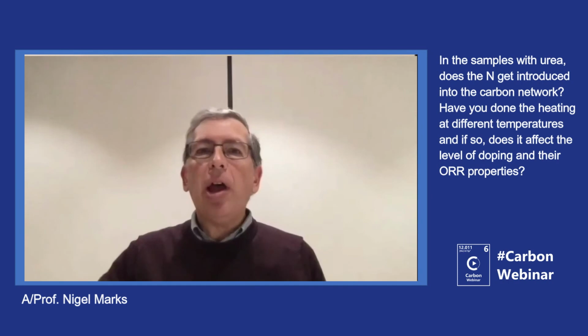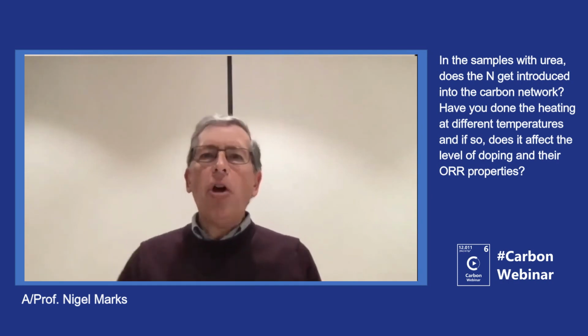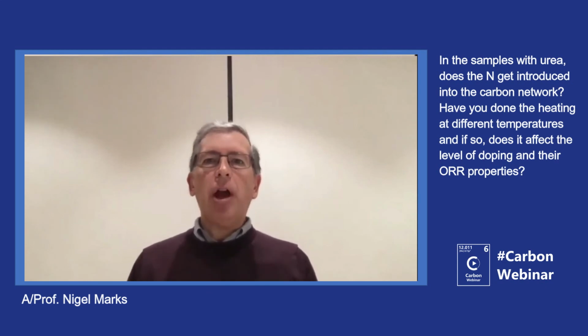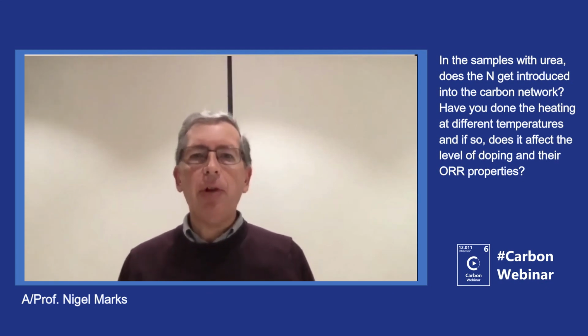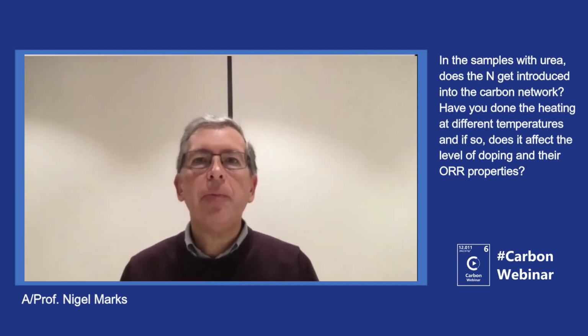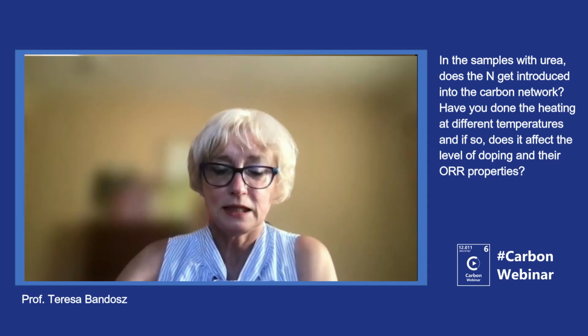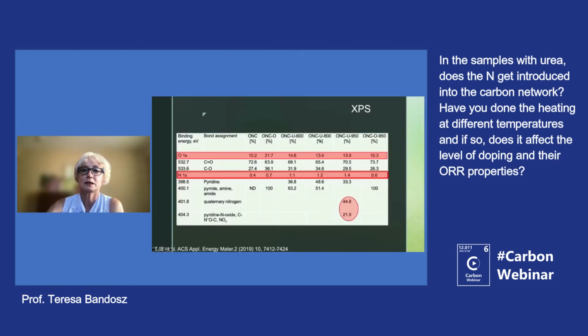Okay, so in the samples with urea, nitrogen gets introduced into the carbon network, and have you done the heating at different temperatures? And if so, does that affect the level of doping and their properties? Yes, we did, and as you can see, we heated them at 3 different temperatures, and we slightly affect the nitrogen content. So basically, I think it is the same, but we affected the distribution, especially in the case of this carbon. So we noticed the differences. We have the quaternary nitrogen, we have the pyridine and oxide.